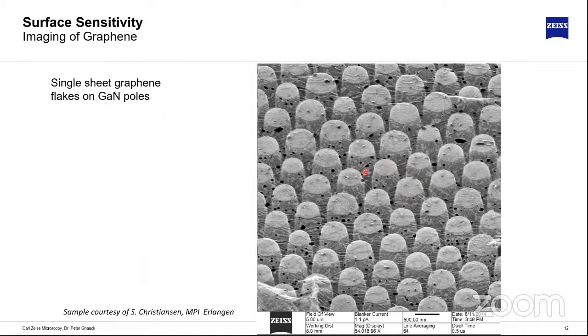And this leads to interesting things that we can actually image single sheet graphene. So this is a monoatomic layer of graphene spanned over these gallium nitride poles, and we can nicely see all these wrinkles, the holes. So it's very easy to really observe at high resolution, even extremely thin samples where you would struggle a lot with electron beams. Here it's a piece of cake. We just take an image at 30 kV and we are extremely surface sensitive.